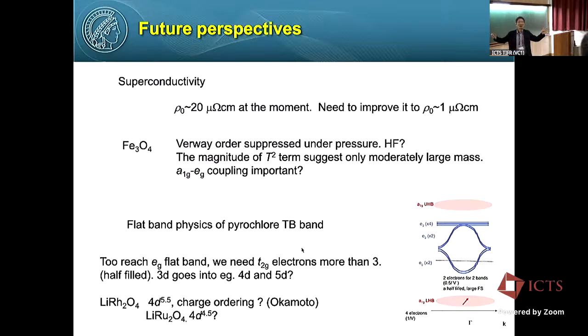remember, we are working on the frustrated pyrochlore. If there is no charge order, the spin channel is frustrated. In fact, in a charge order state of thin film, we did this lithium beta NMR technique, and we did see magnetic ordering there. So associated with charge ordering, magnetic order is induced. So perhaps charge ordering is an anisotropic object, and it suppresses frustration in the magnetic order.